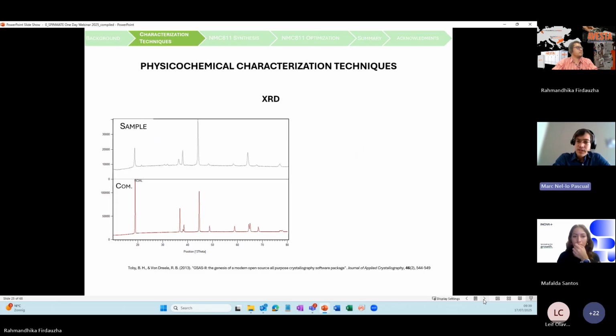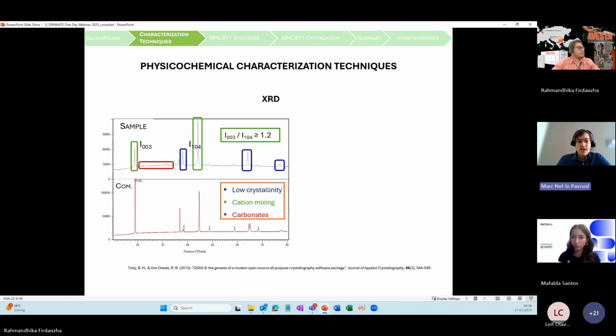So one of the most powerful techniques to be able to do that is X-ray diffraction, where just by simply looking at the patterns, you can take a lot of information. Can you move to the next slide? So from just this pattern, one from a commercial sample and another one of the samples that we synthesized during the project, we can have an idea of the crystallinity of the sample by looking if the peaks are broad, and they are not well separated, they are merged together compared to the commercial sample. You know that your sample has low crystallinity.